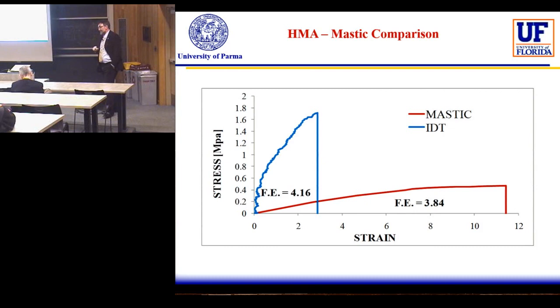The problem is that the general energy. Please, can you repeat? When you talk about the so-called first crack, I would say that if you start to look at the stress strain curves deviating from a linear part, to me that is a micro crack. If you calculate the energy based on that, basically you're measuring energy caused by the micro crack. The fracture energy we are talking about in fracture mechanics is mainly associated with the macro crack